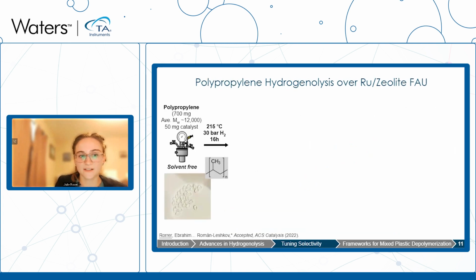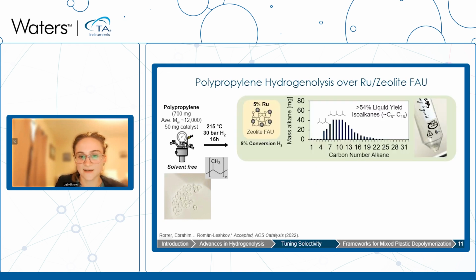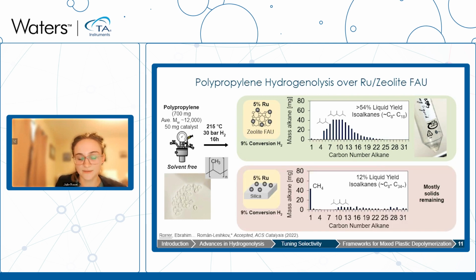And this effect shows up for polypropylene hydrogenolysis as well, where if we compare the ruthenium on the faujasite catalyst at 215 degrees C, we can see a 54% liquid yield for polypropylene deconstruction to isoalkanes. Here's a little picture of the product as well. And if we compare that at the same conversion to an inert support, so a support without the structure nor the acidity, we see that we only get a 12% liquid yield. We're making a lot more methane formation, and we have mostly solids remaining.